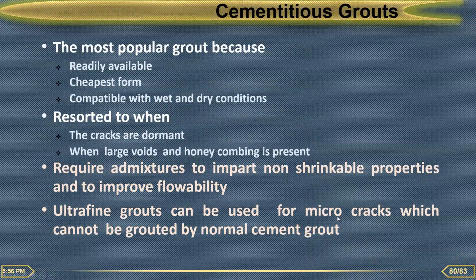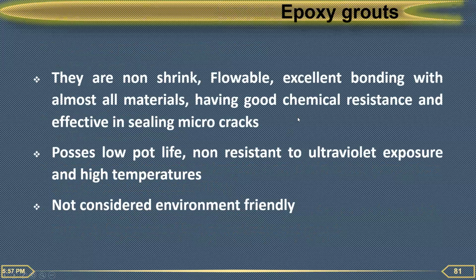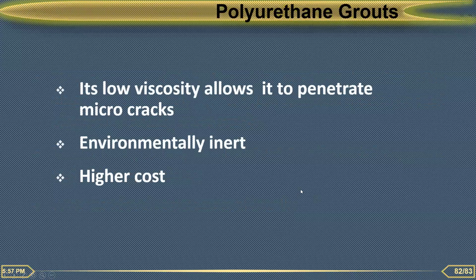Then we have got ultra fine grouts, which can be used for micro cracks and gaps, which cannot usually be grouted by the cement grout. Then epoxy grouts are very popular. Again, they are non-shrink, flowable. They have excellent bonding with almost all materials, good chemical resistance, and are effective in sealing micro cracks. But again, if the cracks are stable, then only it will be effective. Negative points are low pot life, non-resistance to ultraviolet exposure, and high temperature. It is not good for high temperatures. And of course, it is not an environmentally friendly material. Then polyurethane grouts are also getting popular.